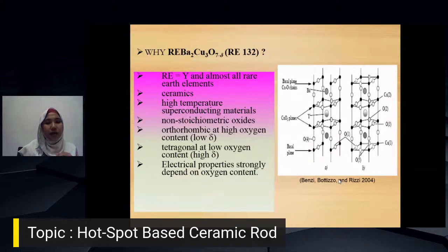Re is yttrium or almost any rare earth element, which can be substituted with the other rare earth elements. This ceramic is known as a high temperature superconducting material, typically a non-stoichiometric oxide. If you refer to the structure, on the top and the bottom planes they have copper oxide chains, meaning they have different oxygen content in the structure. This structure is orthorhombic at high oxygen content, meaning the delta of the compound is very low, then changes to tetragonal at low oxygen content, which is when you have a high value of delta.